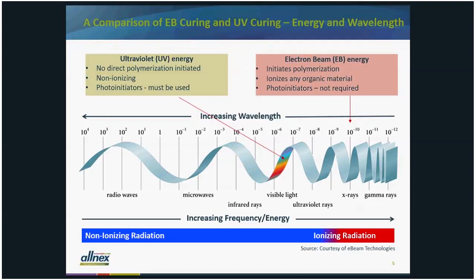This is a big benefit. Scott mentioned that right now a lot of photoinitiators are in tight supply. They're difficult to get, so if you can cure your coatings without worrying about photoinitiators, that's a big plus. There's a few other factors. Photoinitiators are often the most expensive part of a formulation, so you can sometimes decrease your formulation cost by moving to electron beam. And finally, the photoinitiator fragments form a large part of the extractables that can be found in energy curable coatings. So if you're in flexible packaging, for example, and you're concerned about extractables, moving to electron beam can often reduce the extractable content of your coating.